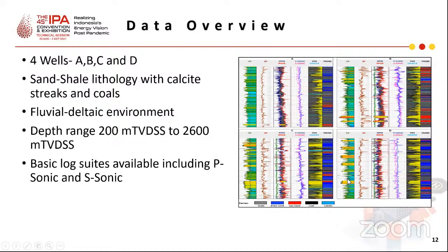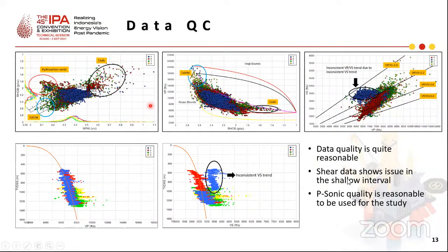The right side shows the log plots with the different available curves for all the four wells A, B, C, and D. This slide talks about the data QC process. We use several crossplots together to identify any spurious data that is present for this formation, or in general, identify the different lithologies. Here is a crossplot of neutron and density. Here we could identify the different calcite streaks, hydrocarbon sands, coals, and in general, the sand shale lithology.